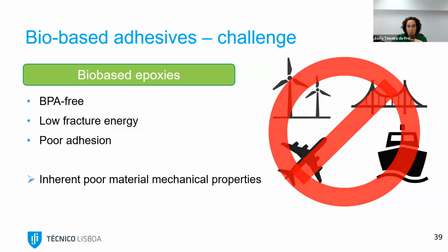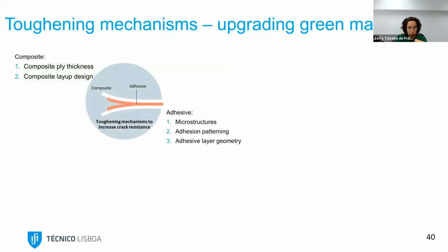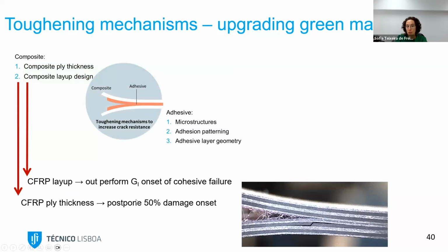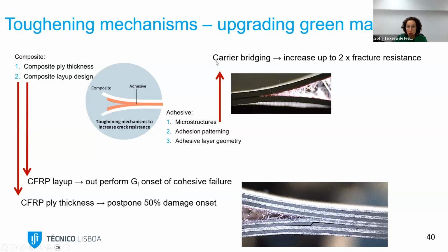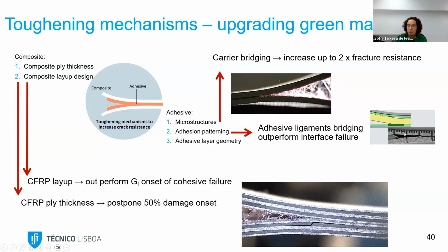So how do I aim to help these bio-based materials? By upgrading them. If you remember from what I've been talking about in the last 40-45 minutes, by changing the composite ply thickness and the composite layout, we could outperform the onset, the damage initiation of the cohesive failure, and we could postpone the damage onset by 50%. And this change in the fracture resistance was without changing anything in the material properties of the adhesive. By adding a mesh inside the adhesive, we could double the fracture resistance. By adding adhesive ligaments, we could also outperform the interface failure. And by changing the layer geometry, we could also tune the crack locus and crack path location. In none of these toughening mechanisms have I changed the intrinsic mechanical properties of the adhesive. I only added different geometries or different substrates that could change the fracture resistance.